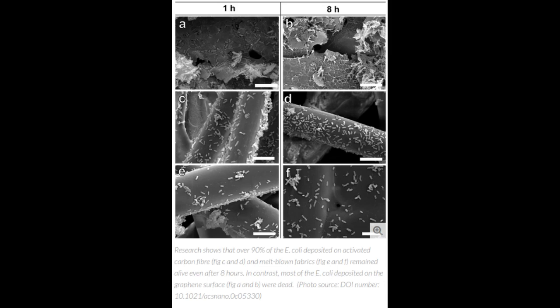Experiment results also showed that over 90% of the E. coli deposited on them remained alive even after eight hours, while most of the E. coli deposited on the graphene surface were dead after eight hours.